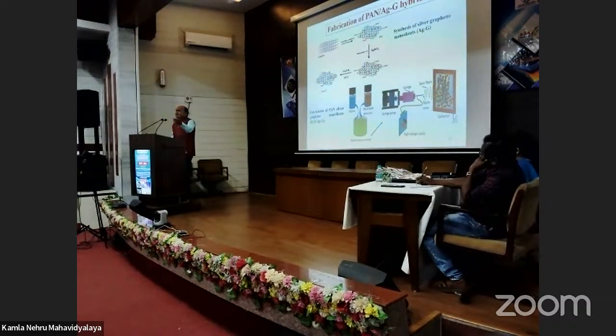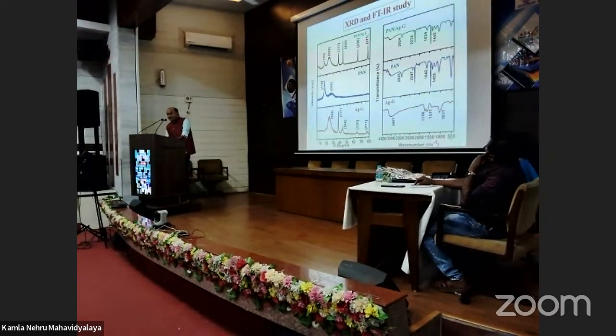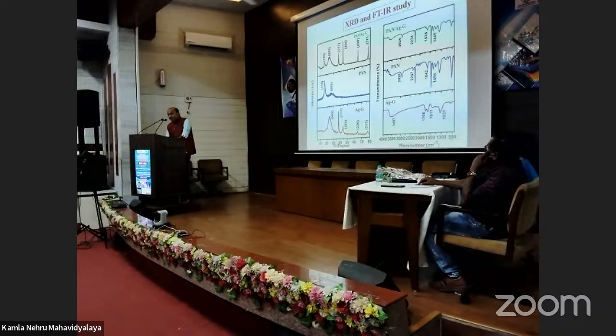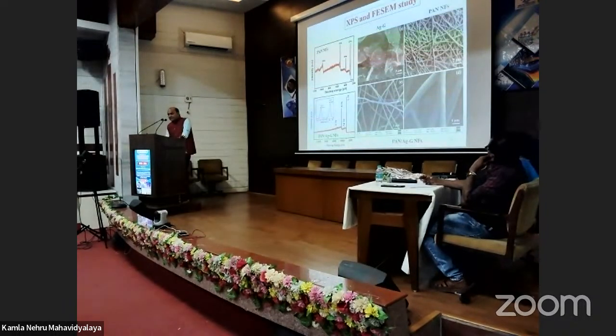And further, those silver graphene oxide particles were decorated over the polyacrylonitrile nanofibers by the help of electrospinning. This is the XRD. I will not go into detail. These are the XPS and FESEM of this particular material. If you look into this, the fibers have a long length.